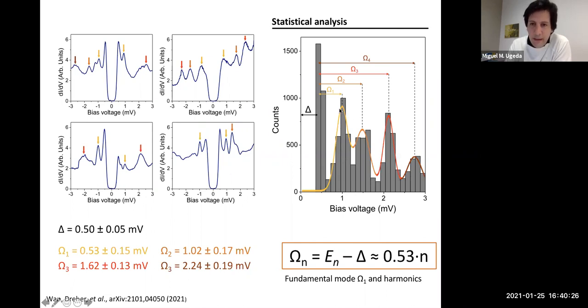And basically the result of the fit of this histogram leads to four values for what we call omega values for these features. We count them from the average value of the coherence peak. I will show you why. We don't usually count from zero, but from the particular value of the curve for the coherence peak value. And from that point, we have omega one, a value of 0.53 millielectron volts. Omega two is 1.02, 1.62 for omega three, and actually this is omega four, 2.2 millielectron volts.